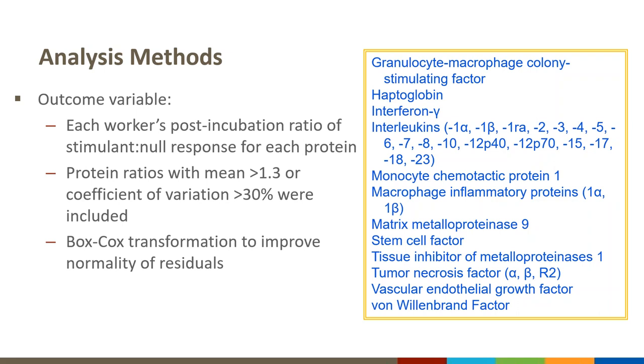In addition, in the few studies that have been done, mostly among healthy people, using the TruCulture methodology, the stimulant null response ratio is the metric of choice there. We included for analysis the protein ratios that had a mean ratio of greater than 1.3 or that had a coefficient of variation of greater than 30%. And the reason we selected this is that we didn't want to include non-responsive proteins in the result, since this was really looking for biomarkers that show a response when stimulated with these strong bacterial stimulants. We used Box-Cox transformation to improve the normality of the residuals in all of our analyses.